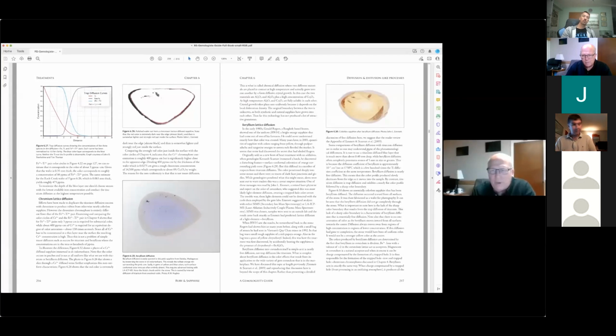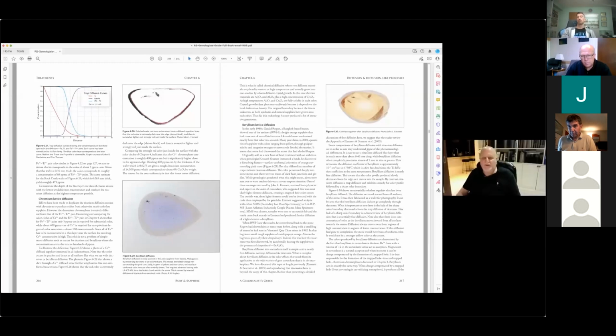I was told at one point that some people are using one of these treatments, like a heat treatment, to almost melt, if not melt and recrystallize the inclusions in the star stones to give them a cleaner and more well-distributed silk. Is this also what's going on, or is that just something I heard it wasn't? Well, it is possible to diffuse titanium into a sapphire, and then if you do it in the right way, you will create silk under the surface of the stone. And that's a titanium diffused star.